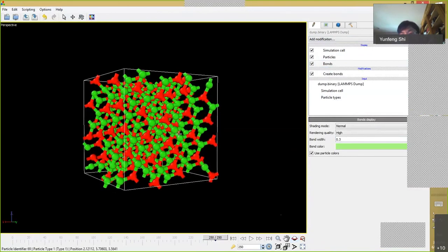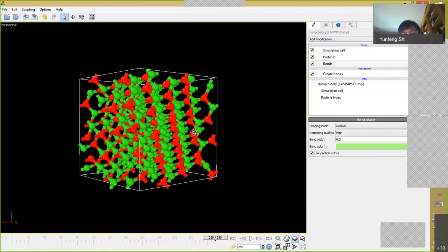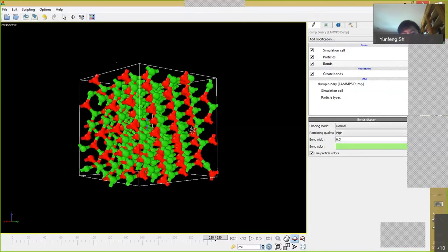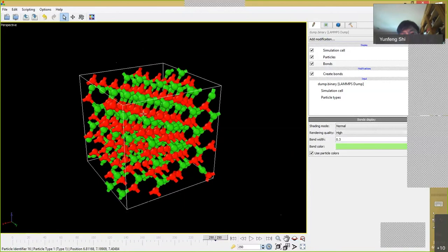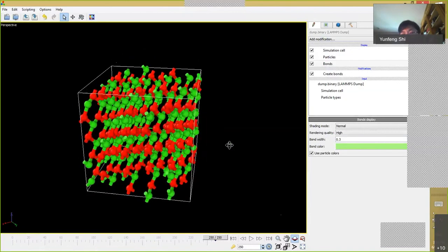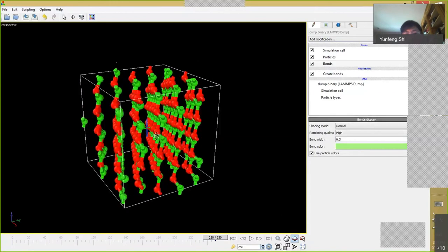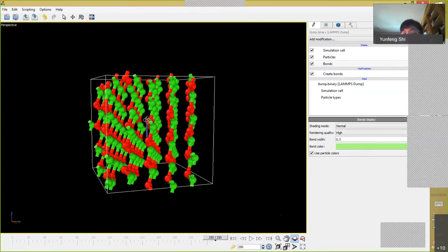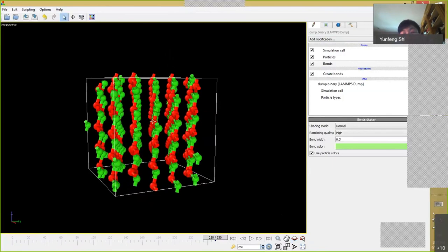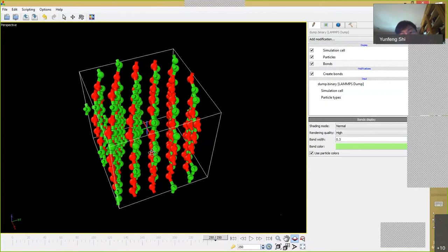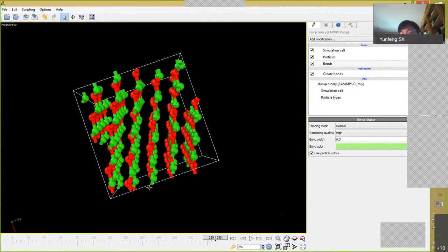Look at this. Anybody knows what the structure is mostly similar to? Look at the connectivity, right? This atom, the green, is connected to three red. And red is connected to three green, right? This is almost like boron nitride, but corrugated. It's not planar, right? Now, this is completely pair potential, right? But it can have this very, very covalent-like structure coming out, okay? All right?